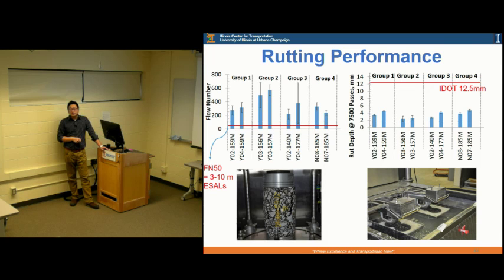We're also using flow number and also Hamburg wheel tracking. This line is pretty much a threshold. So for flow number, we want the flow number higher to get a better rutting resistance. In this case, the minimum should be 50 for traffic ESALs of 3 to 10 million. So you see they are much higher than 50, which means all the mixes have no issues for rutting.